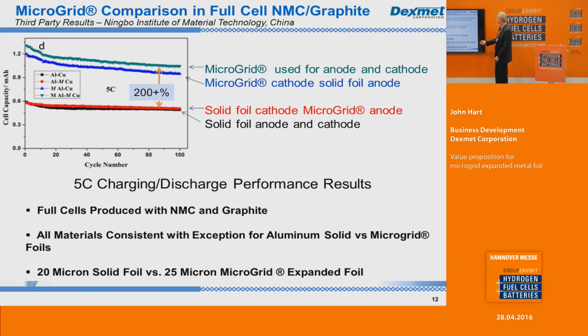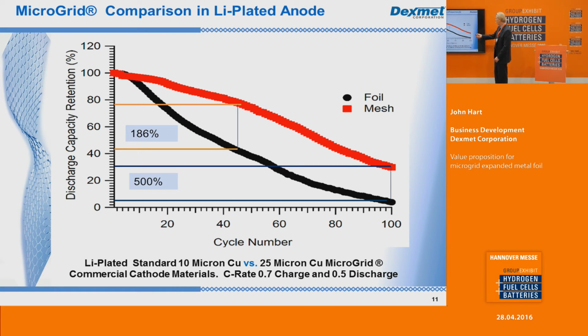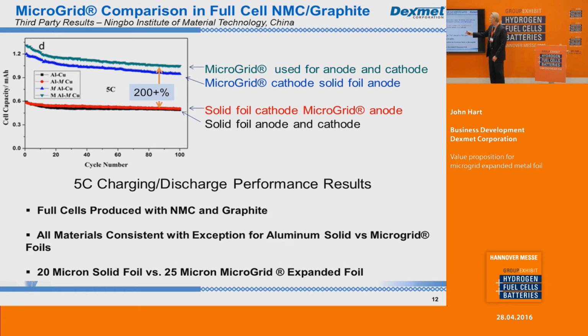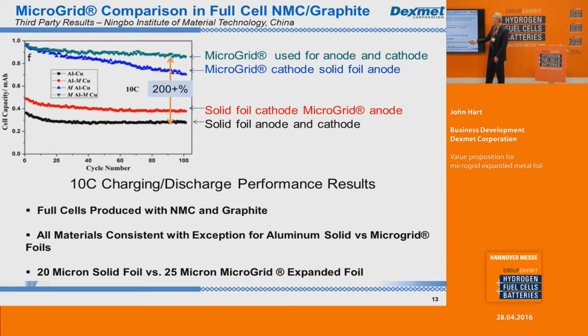Just back up here a second. On this study, you'll note this was done at 1/2 C discharge rate. This study was done at 5 C discharge rate. And this study at Ningbo was done at 10 C discharge rate with the same results, more than 200% available capacity using expanded metal on both the anode and cathode.